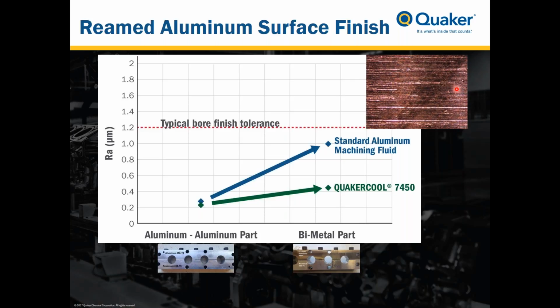And just to show the finishes obtained, again, earlier we saw the finish of the bimetal part using the standard fluid. We noted the general graded roughness and the scratches that can be observed. And then if you look at the ream finish utilizing QUAKERCOOL 7450, you can see a very good quality surface, minimal light scratching, but overall a very smooth and consistent profile on the surface.